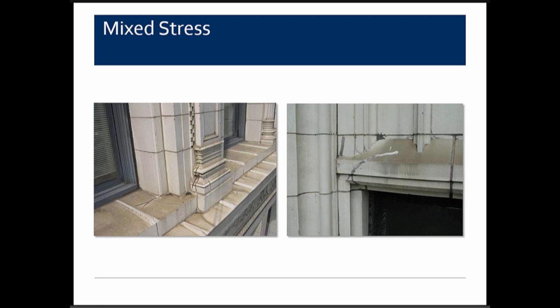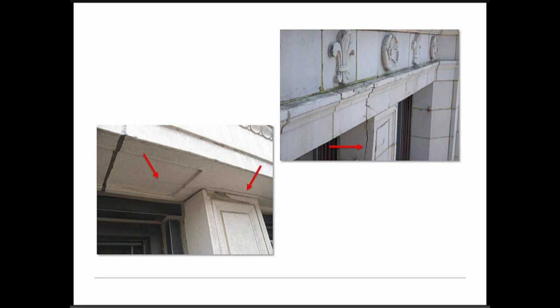Mixed stresses can occur — it's not always one thing causing failure. At the bottom of a pier and the corner of a lintel unit, you can have stresses from changes at openings combined with corrosion of underlying steel. Sometimes compression just cracks the pier or causes it to punch into the lintel, creating cracking on the soffit and side of the pier.